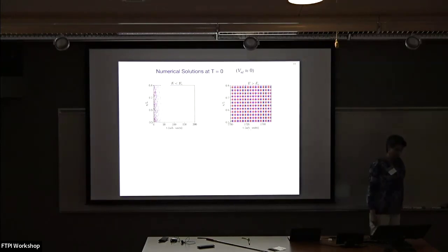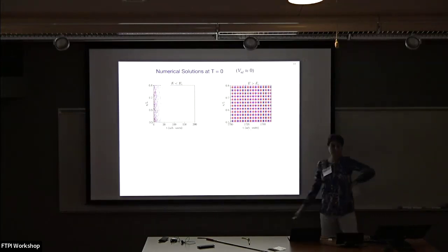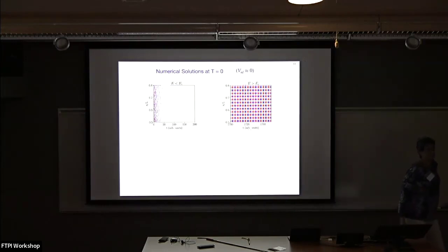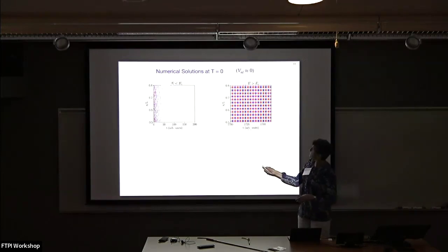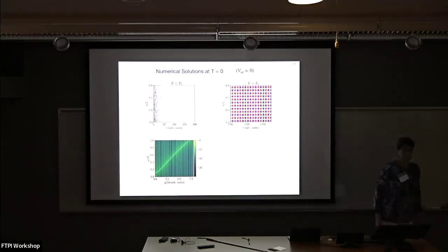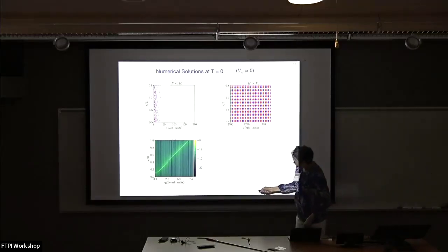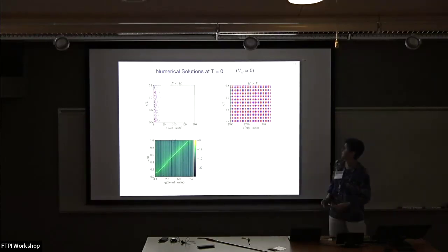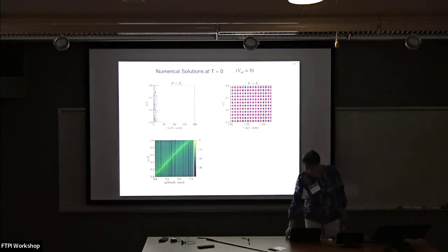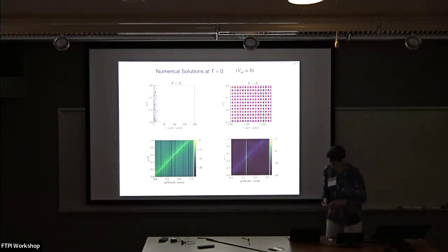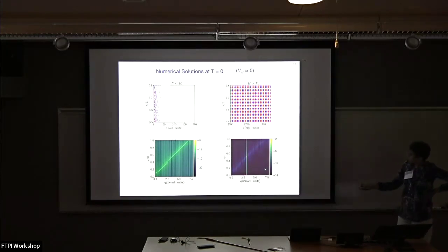Now, of course, as we know from our scattering codes, a lot of information is stored in the structure factor, in particular about the interaction between the modes and the dispersion. So what happens if we look at the log of the structure factor? We see this dispersion. And that's it. But what happens for E greater than EC? Well, that's quite dramatic. You notice this is a logarithmic scale, and what we see is this parametric resonance.